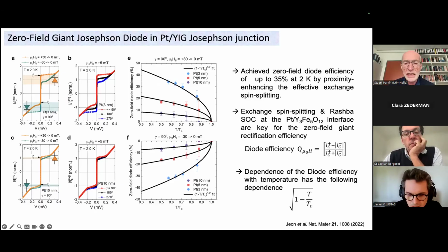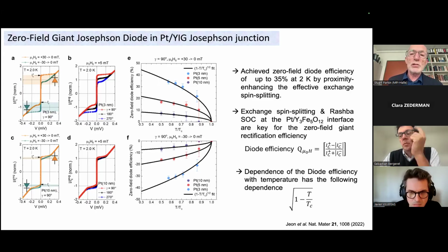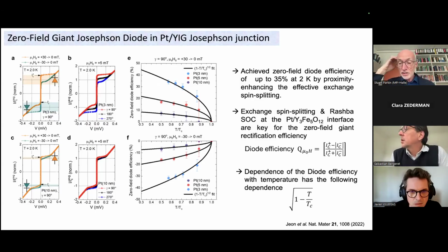And I do want to point out that the temperature dependence of this effect is very different from the temperature dependence I introduced earlier. Earlier, I showed it varied as T minus T to the power 2. Here, it varies as 1 minus T upon Tc to the square root of that. So it's very different. So the dependence of the diode efficiency with temperature has a very different dependence.